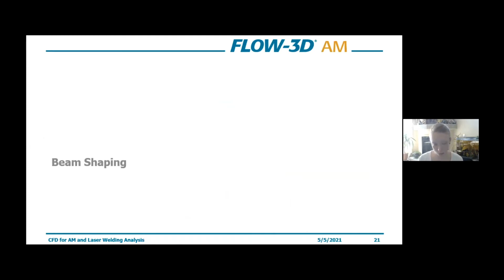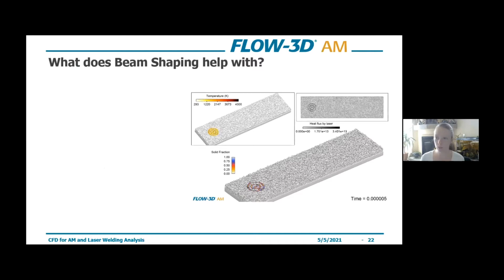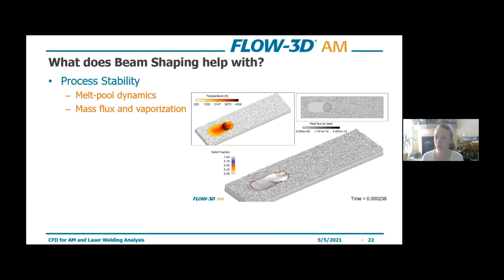So looking into beam shaping, which is, I think, becoming more attractive as a way to increase process stability and have a little more flexibility in terms of how you're printing. So what does it help with? Melt pool dynamics, having a more quiescent melt pool, having lower velocities just in general, and mass flux and vaporization. So we do want to kind of lessen this as much as possible. When you have high mass flux and vaporization, you're going to have higher recoil pressures, and that can lead to spatter, porosity, as we saw in the previous example, and some other issues. So beam shaping is a good way to increase process stability.